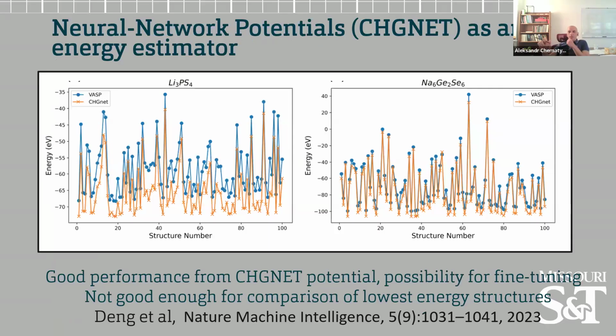The last thing which I want to point out, and I'm getting close to time. Oh, excellent, yeah, exactly. The last thing which I want to point out here is we came across this neural network set of potentials. I was originally fairly skeptical that it might work, but what you see on the plot here is a comparison against DFT methods. I know it's typically shown as a parity plot, that's a different type of plot, but we decided to show it this way. Nevertheless, this neural network potential has a very decent accuracy in predicting the energies of our system.